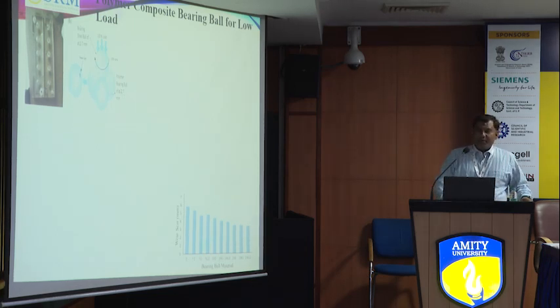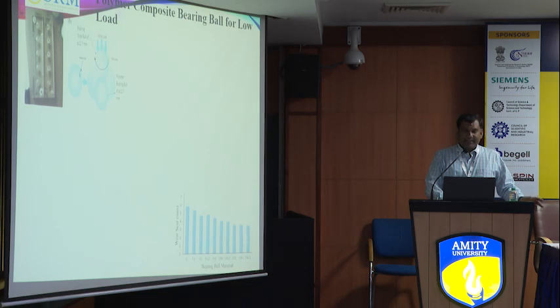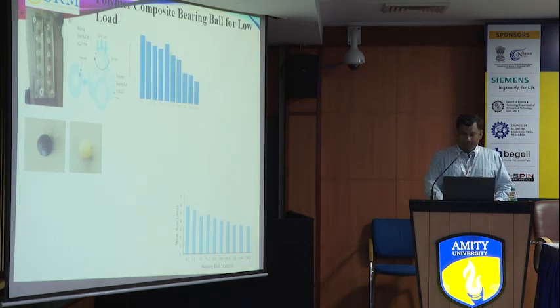So if we can make polymer, ceramic balls, and steel balls, so why not polymer bearing balls? That was the biggest challenge, how we can develop them. We can make the acrylic hemispherical mold through milling, and then we can make these bearing balls. That is a standard 12.7 mm diameter. These balls we can test in a four-ball tester.